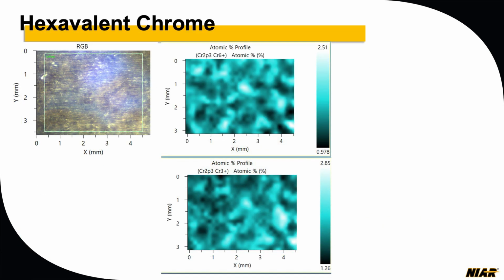So on the whole distribution, you can see the Cr6 distribution and the Cr3 distribution. There's a possibility that the Cr6 has been converted to Cr3 in some of the areas where there is less deposition, visibly, what you can see. So this is just an initial analysis. This is what we found, and that's what I'm showing you right now.